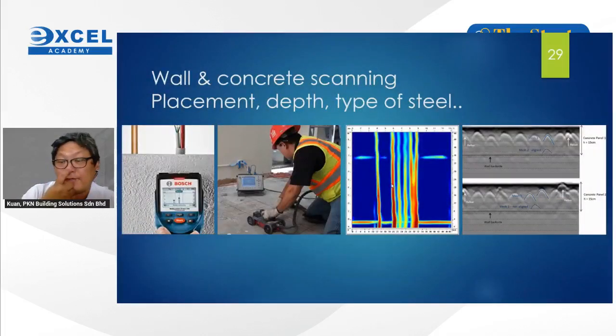And even for concrete, okay, now we go to the heavier part. Concrete. A number of studies actually reveal that abnormal cracks in concrete always come from either misplaced, missing, or undersized reinforcement steel bar. And by doing concrete scanning, we can locate the position of the reinforcement steel bar, the diameter of the reinforcement steel bar, and even the type of the steel.